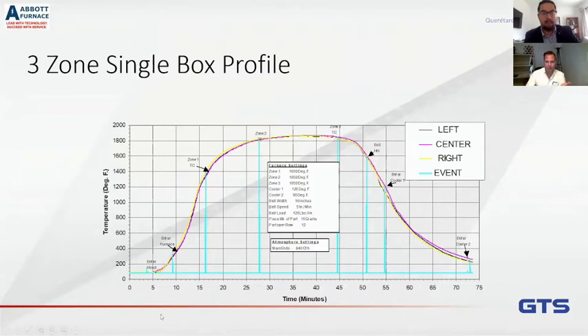we have plotted temperature versus time on the bottom axis, and all this is you place a thermocouple in a part or in a fixture, and you measure the temperature as a function of time going through the furnace. Now, one thing you need to be careful of when you do these, one mistake that people often make is that they plot temperature versus distance. And depending on the speed that you're traveling through, you could end up with graphs that look very similar, but the actual time that you are at temperature is significantly different. Right. So you always plot temperature versus time.